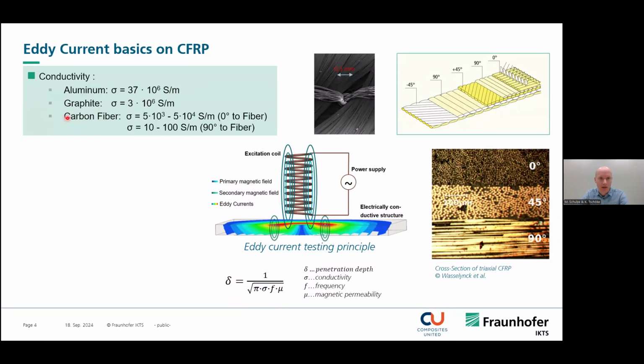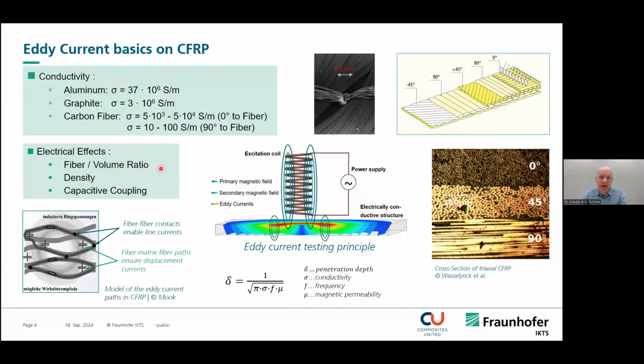When we have a look at the carbon fiber, based on its anisotropic behavior, we have different conductivities along and across the fiber. This so-called anisotropy comes from the contact points. So we have a resistive part in the fiber, and also capacitive components that describe this anisotropic behavior of the material.